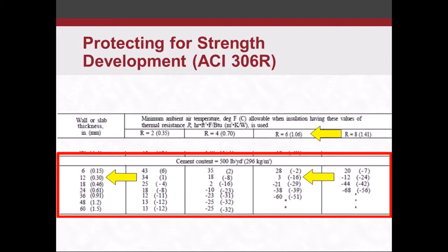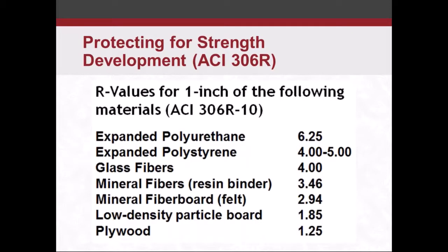Those R values of 6, you're probably asking yourself, how do we know what R values we have? Our good old ACI 306 gives us some information on that. Here we've got R values for 1 inch of the following materials: expanded polystyrene, polyurethane, glass fibers, mineral fiber board, plywood. So if you think of about 3/4 inch plywood formwork, we can get about an R value of 1 just from the 3/4 inch plywood formwork. And then we put a couple of blankets on it, maybe blankets that are 1 inch thick or something like that. We're getting pretty close to our R value of 6.